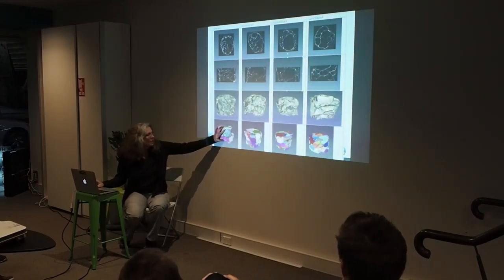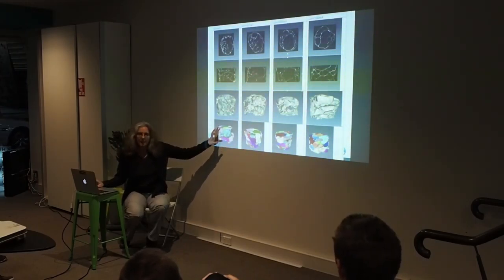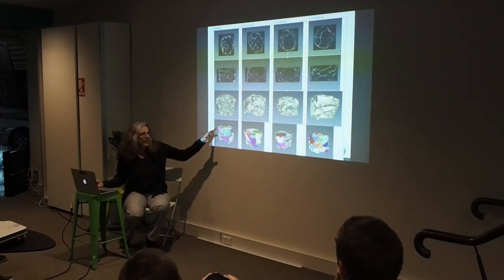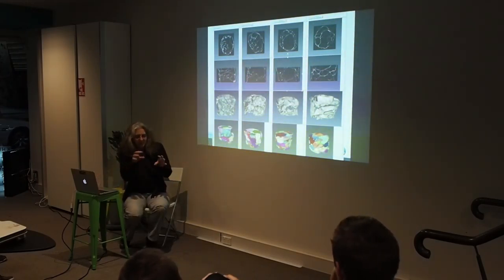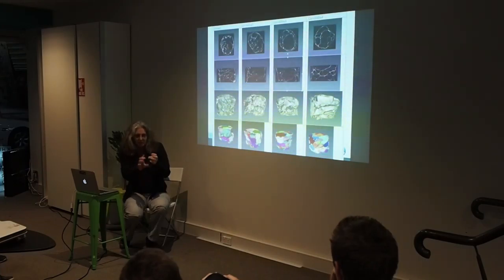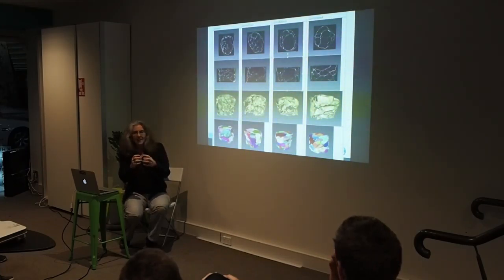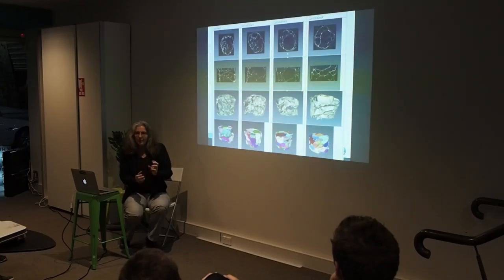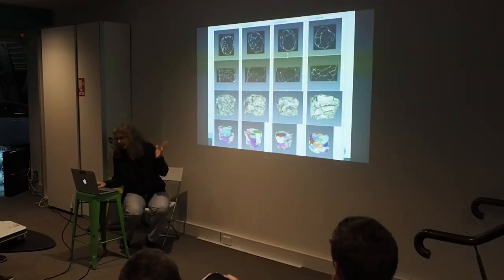What I'm visualising here is segmented data, where I've gone through and analysed it, identified all the pores, separated ones that are a bit joined together, and then they're all labelled separately so we can measure their volumes and surface areas and anything you want.